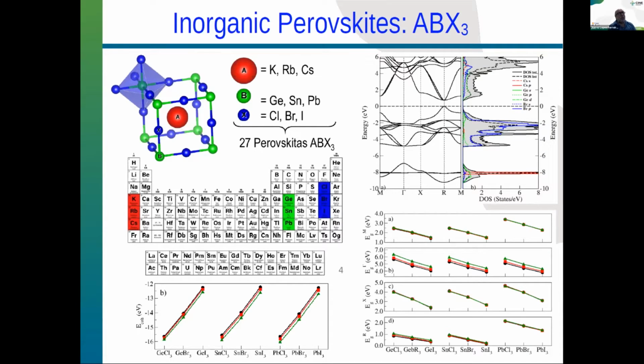I show here an example of the band structure for you, on the left of your screen. As you can see here, it is a material that has a semiconductor behavior, which should be expected, otherwise we will be in trouble. Okay, but then we identify all the components of the states that play a role. And as you can see here, the halide p states play a very important, dominant role in the top of the valence band. And then also different compositions of the states too.